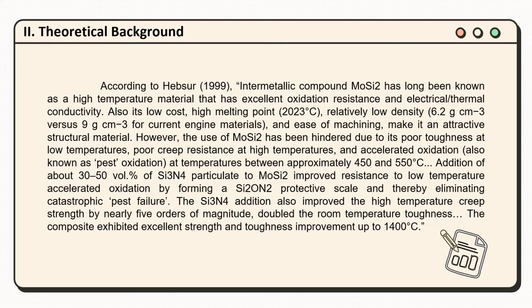Addition of about 30 to 50 volume% of silicon nitride particulate to molybdenum silicide improved resistance to low temperature accelerated oxidation by forming a silicon oxynitride protective scale and thereby eliminating catastrophic pest failure. The silicon nitride addition also improved the high temperature creep strength by nearly 5 orders of magnitude, double the room temperature toughness. The composite exhibited excellent strength and toughness improvement up to 1400 degrees Celsius. This relatively supports why the research study exists.